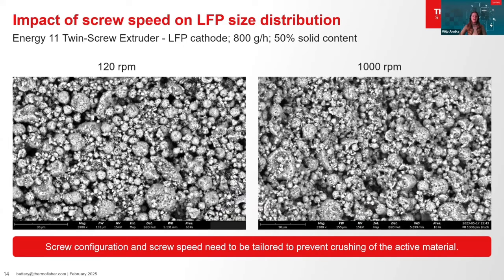Here you see an LFP cathode. The LFP size distribution was widened and decreased because this screw design led to breakage of the LFP particles. The effect increases with higher screw speed due to higher shear, and it's probably not a wanted effect. These two examples show that the screw design and the speed need to be adapted to the specific materials. When a suitable screw and process design is developed at the end, the next step is to scale it up. Some guidance is given now in the next slide.